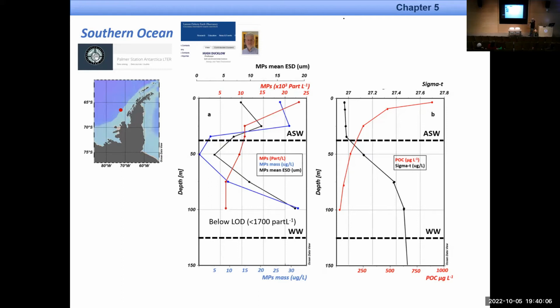And then an important thing with the mass is we found a peak around 100 meters in mass. And also that is related to the size of the particle. Bigger particles we found here at 100 meters. So bigger particles are going to give you bigger mass.